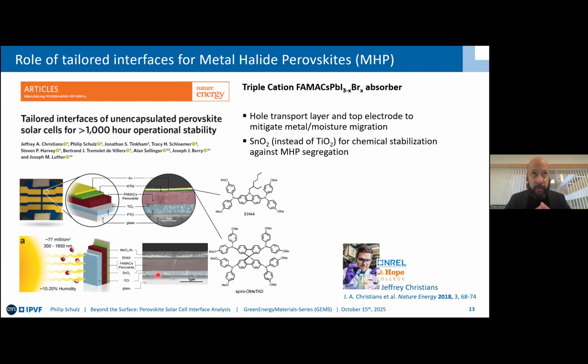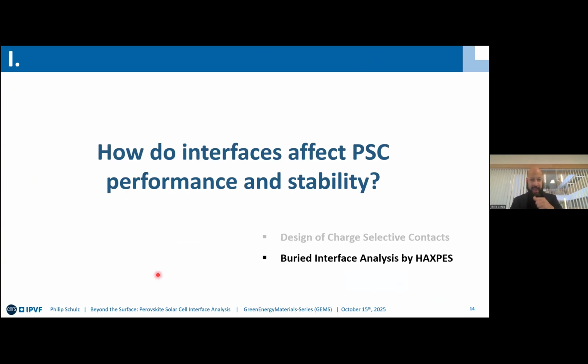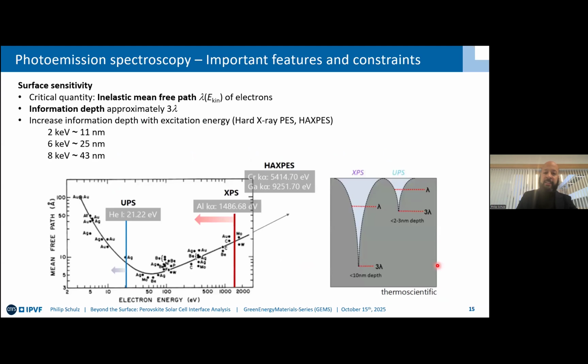So it's something that we were very ready to observe qualitatively, but quantitatively, and pinning down exactly the process on what occurs at this interface that stops this segregation and degradation effectively has been an open question for a long time. And therein comes now how we need to hone our tools in order to get to these interfaces. So how do interfaces affect perovskite solar cell performance and stability? I ask again. And this time around, I'd like to present on how we get to this interface by HAXPES analysis.